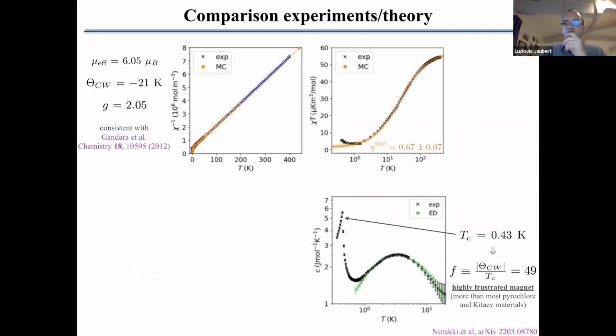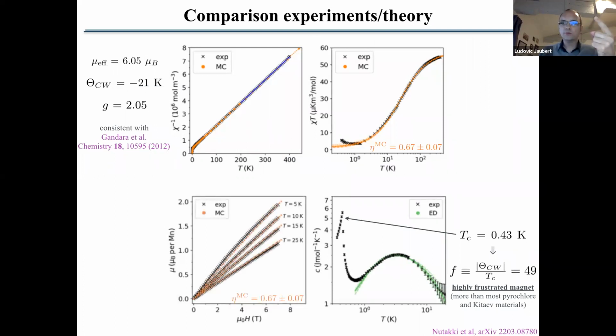So essentially, since you have a model with only two parameters, the ratio of the two is the characteristic parameter that will describe the physics of the model. And so this value of eta in ab initio calculations and in Monte Carlo simulation compared to magnetic measurements give us roughly the same value. And if we do some rough exact generalization approximation to model this bump, we also find a similar value of approximately 0.6. And this bump here, that's essentially the onset of quantum correlations. That was also observed in ytterbium titanate and in many pyrochlore systems. You have a bump at a few Kelvin, and this bump corresponds to the onset of quantum correlations at the level of one tetrahedron. So above this bump, that's essentially paramagnetism, and below this bump, that's the onset of quantum fluctuations.